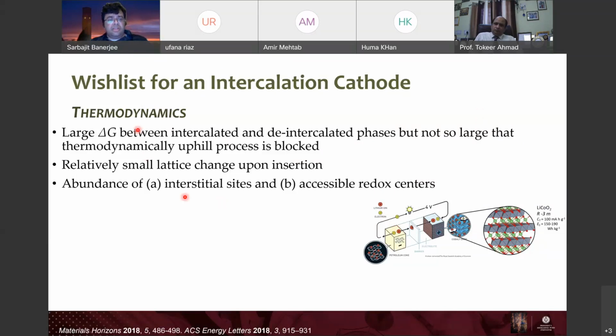So in general, this again comes down to a play of thermodynamics and kinetics. You need to have a large delta G between intercalated and deintercalated phases. So for example, between lithium cobalt oxide and cobalt oxide, right? And it should be large because why? Because delta G is equal to negative nFE, right? So if delta G is small, the actual cell potential that you get out of it is going to be small, so you're not going to get very much voltage out of that, right?